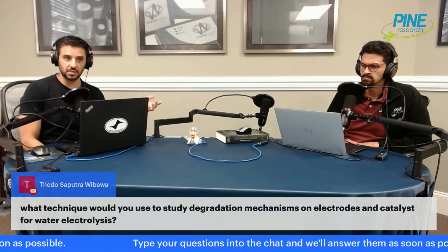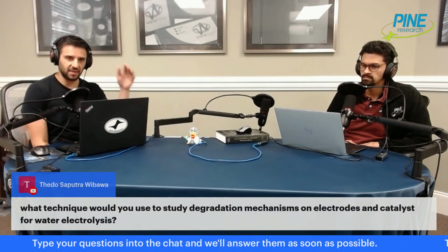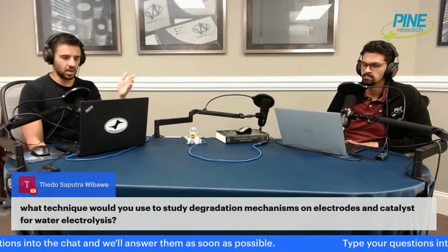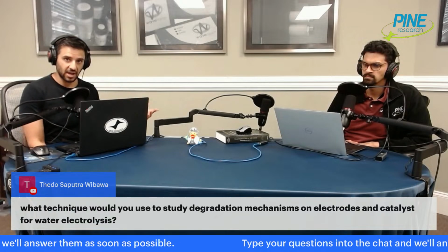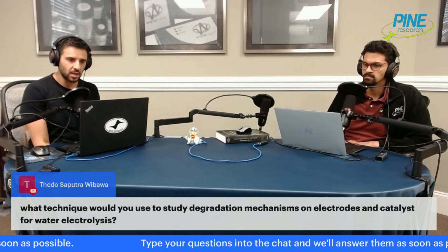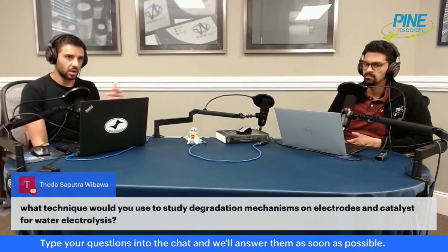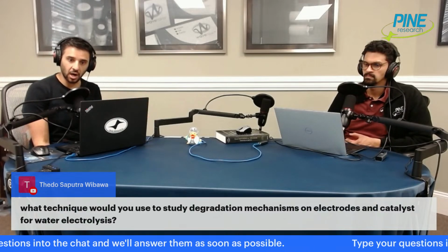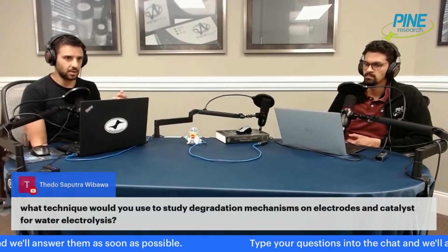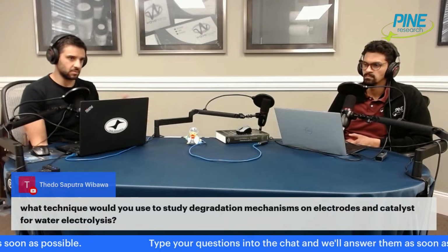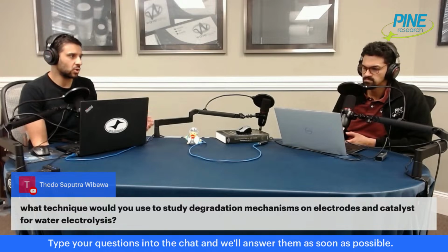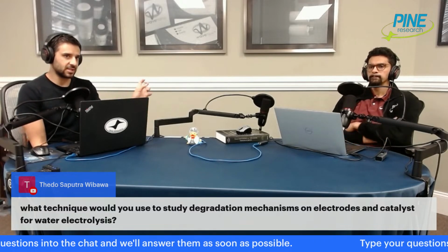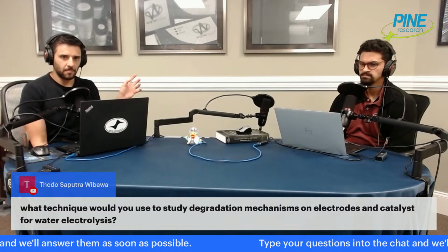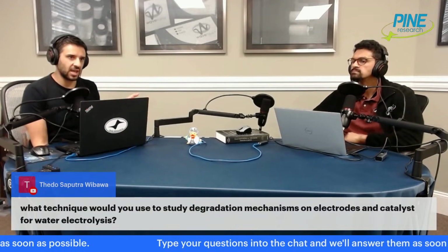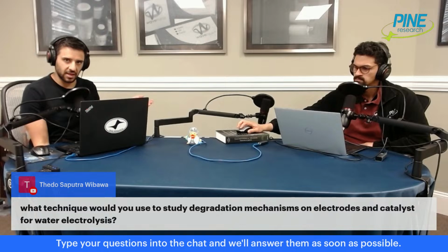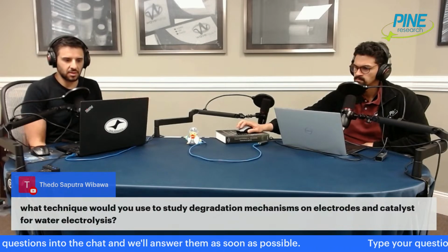Impedance you could use, for instance, to measure like the charge transfer resistance. Pick a faradaic potential of the oxygen evolution or the hydrogen evolution reaction. Pick a potential where that's occurring, and measure the impedance of your electrode of the OER, of the HER, whatever. You'll get like maybe a semicircle, maybe some diffusion, maybe whatever. You'll measure some resistances, and you can measure over time, if the resistance starts to increase, it could indicate degradation. It could indicate a lack of catalytic activity. So those are some of the ways that you could do that.